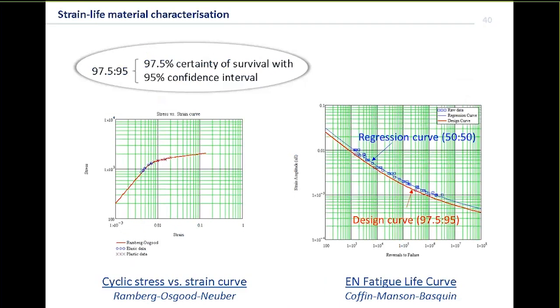So in strain life, we actually need not just a curve, a fatigue curve, but we also need that relationship between stress and strain. And the reason we need that is twofold. Firstly, when we consider things like mean stress correction, if all we're doing is measuring strain, we need some way of finding the stress in order to do the mean stress correction.